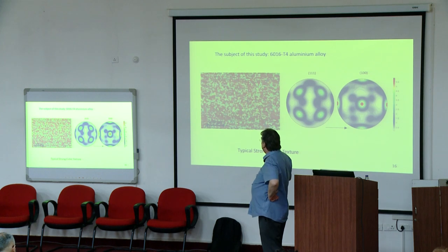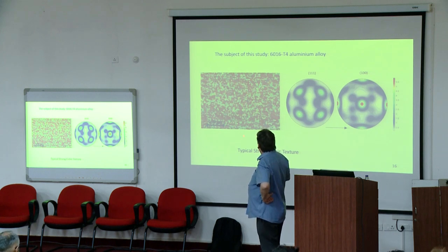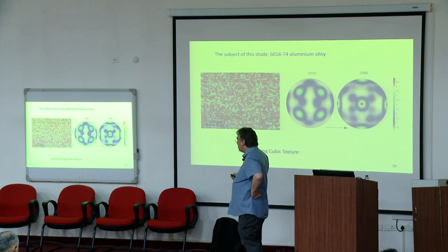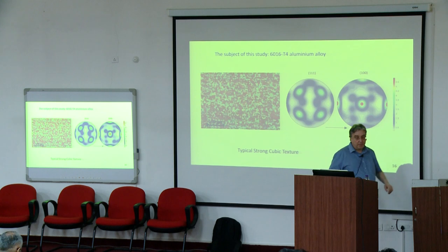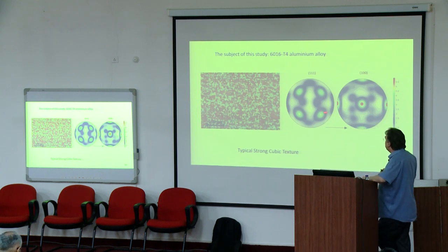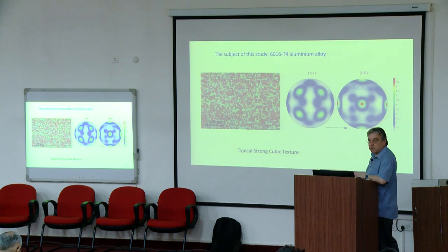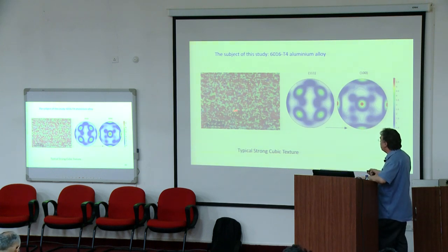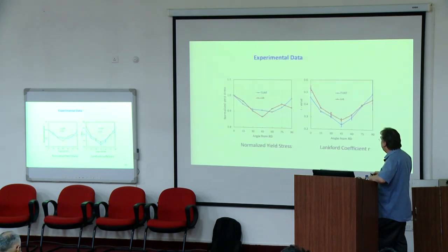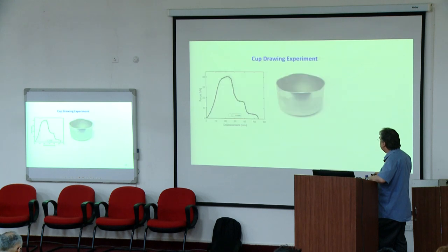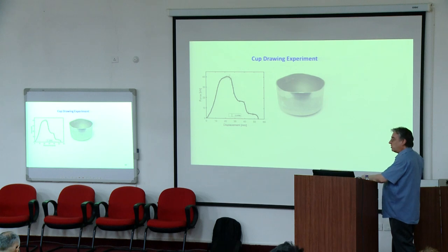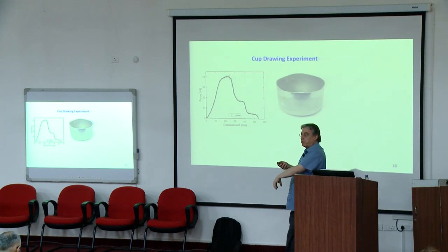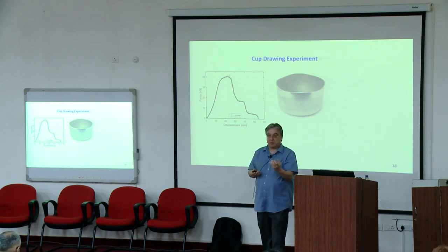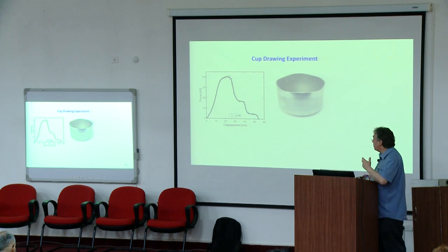So an experimental test was done, and this was the initial microstructure. This was for a 6016 aluminium alloy in T4 natural aged condition. And this has a very typical strong cube texture. Actually, I think it should be red, but it is discolored a little bit. So red is typical for cube texture orientations. And do I have a separate picture? Yeah, here. This is a cup drawing experiment. So you have a circular blank, and then with a die, you punch through that circle, and you obtain a cup type shape.